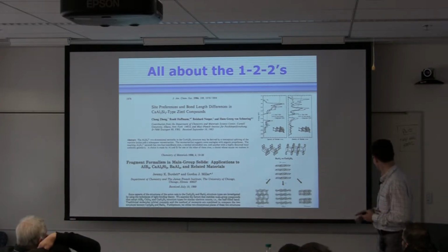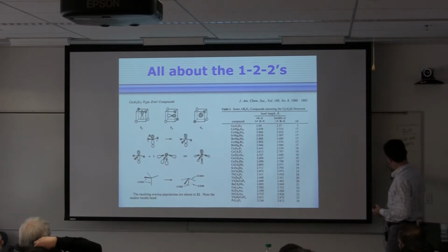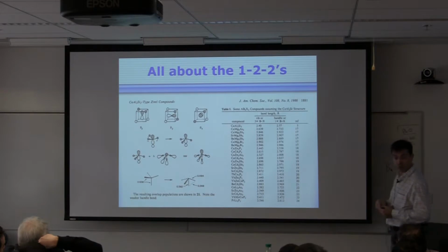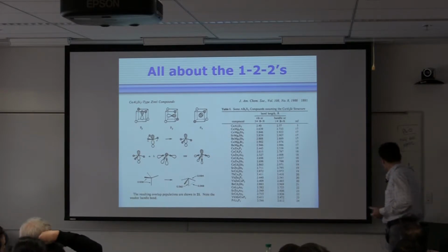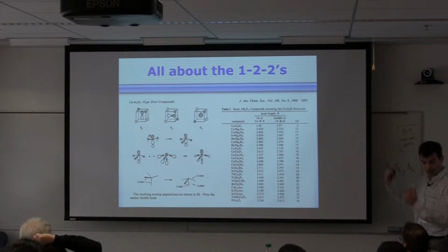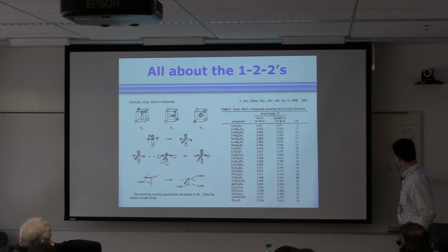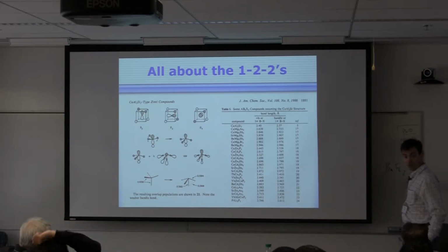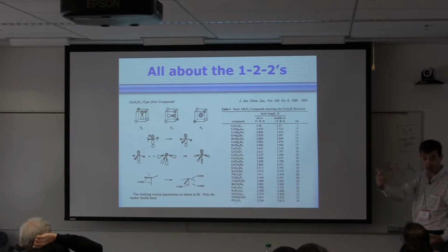Because even if you think about barium, iron, and arsenic too, this compound is also a 16 electron system. And the way that you would change the electronic structure and form those collapsed structures is by doing substitutions on this side or this side, or you can substitute the barium, which is how this was originally done.